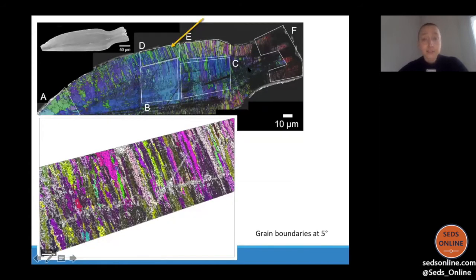And in order to analyze this, we need to be able to measure the size of the grains. And this is where my uncertainty comes in, because I will be showing you things that we have not resolved yet. So I would really appreciate any opinions or advice from all of you in terms of how to identify the real size of crystallites in a biomineral that is not actualistic. It does not have any reference. So if you try to resolve the grains, usually you assume a certain misorientation between adjacent grains. So if two adjacent areas have a misorientation larger than, for example, 5 degrees, we treat them as separate grains.